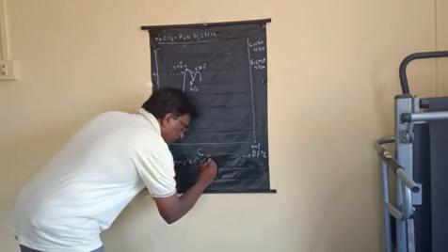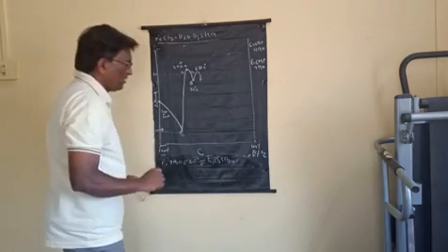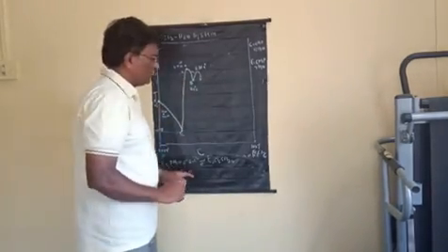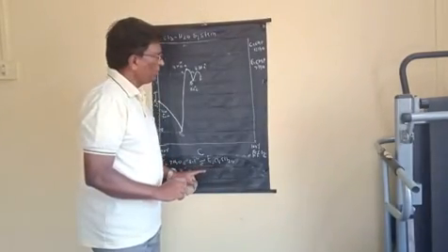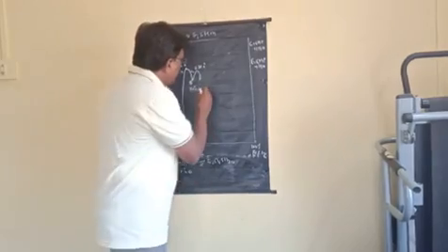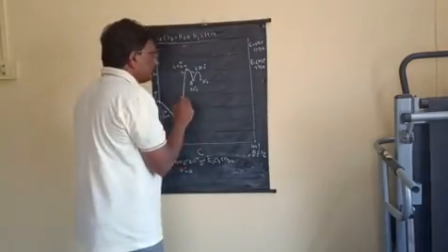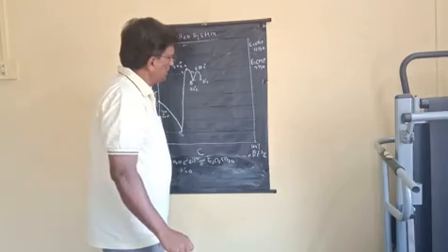The previous phase 7H2O, the solution, and the new compound that separates out, that is Fe2Cl6·5H2O. As 3 phases remain in equilibrium, it is a triple point, and here the system is non-variant according to the reduced phase rule. The system is non-variant. Now, the temperature of this particular point F is 30 degrees centigrade.